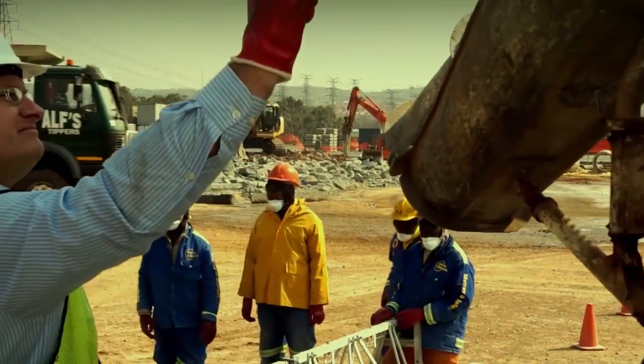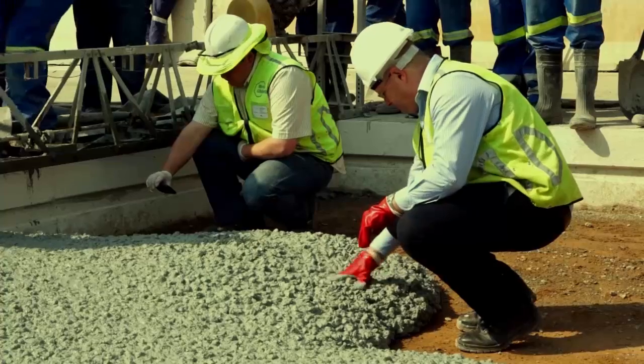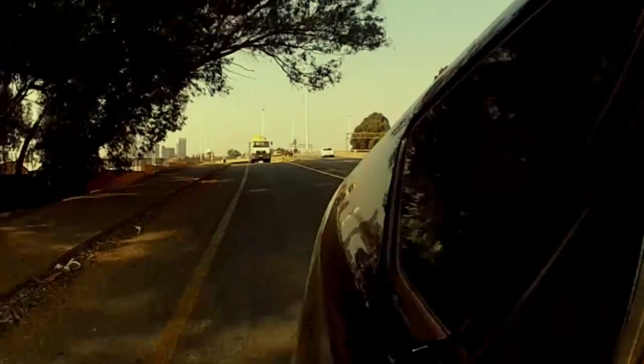The second truck comes back with 4 cubic meters of material. We load it up and we attain a 180 millimeter slump. The truck is now going to go pick up a 6 cubic meter load, the largest load.